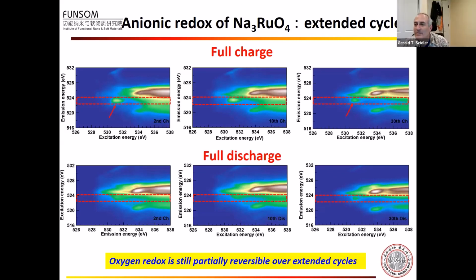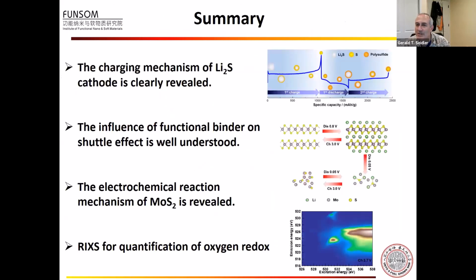Very good. What do you see as the spectroscopic challenges that you would most like to overcome in these sulfur-rich materials? You've learned a lot about the sulfur redox cycling. Is there some limitation in the spectroscopy that you would like to get past? Whether you need more flux or more focusing, or you need RIXS, what would make your science stronger? One thing is, if possible, I want to measure time-resolved sulfur K-edge, because the redox reaction is sometimes very fast, and at the moment each spectrum takes about 15 minutes. Maybe some reaction has already happened in this time period.